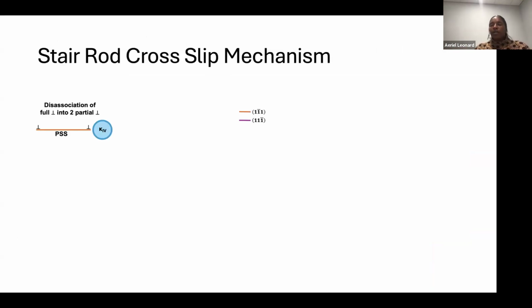But what we've learned from other materials like TWIP steels, or some of the high entropy alloy work that Mike has done, is that you actually can get partials to cross-slip by forming a sessile stair-rod dislocation. So from a mechanistic point of view, you have a full dislocation that's dissociated into two partials. The leading partial shears the precipitate, the trailing partial, in some cases, gets stuck. So now we have an intrinsic stacking fault that is formed.